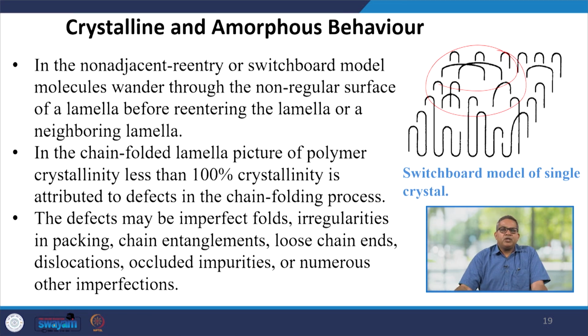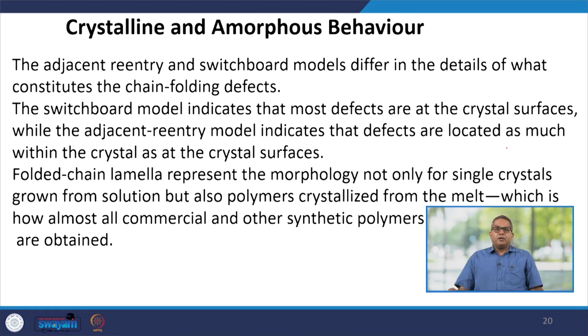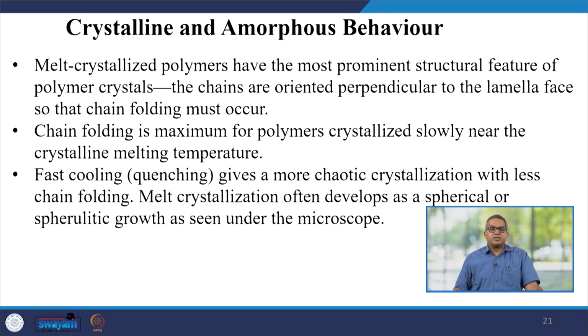In the chain folded lamella picture of polymer crystallinity, crystallinity of less than 100% is attributed to defects in the chain folding process. Now, these defects may be imperfect folds like this, irregularities in packing, chain entanglements, loose chain ends, dislocations, occluded impurities, or numerous other imperfections. The adjacent re-entry model, like here, and the switchboard model differ in the detail of what constitutes the chain folding defects. The switchboard model usually indicates that most defects are in the crystal surfaces, while the adjacent re-entry model indicates the defects are located as much within the crystals as at the crystal surfaces.